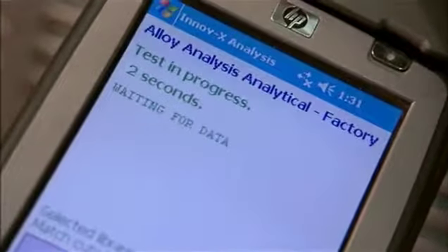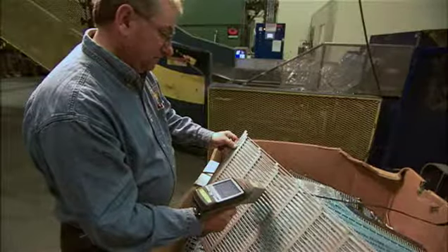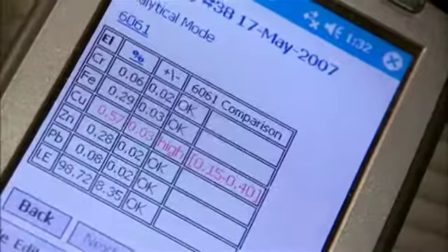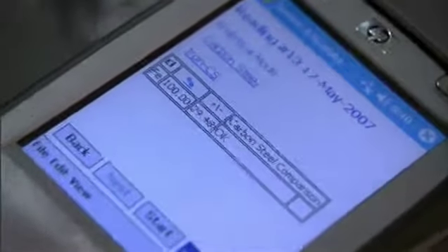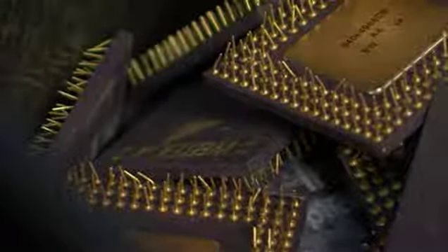Determining the exact makeup of alloys is the first step. It's an X-ray device that identifies the metallic content of an item. It only identifies the metallic content, so if it's a mixture of plastic and metal, it'll only tell you the metal that's in it. So we scan all materials coming in, all different types of base metals with that gun to determine the type of metal it is. It could be an aluminum, a copper, a stainless steel, a tin, a nickel. The gun will allow us to QC that in the door, so we're not guessing or using other types of simple tests to determine the metallic content.